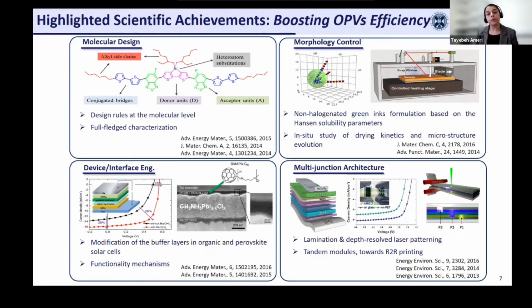In addition to the material design, we were working on understanding the drying kinetics and the morphology control of our photoactive layer, this blend of donor and acceptor, to optimize that. And this photoactive layer is always sandwiched between the hole and electron transport interface layers and cathode and anode. So we need to put a lot of effort also on the device and interface engineering to modify them for the best extraction and functionality.